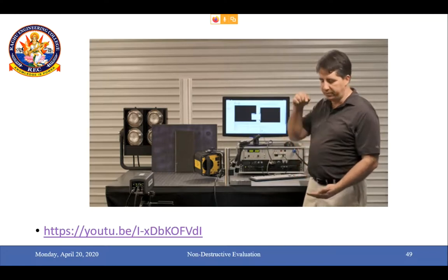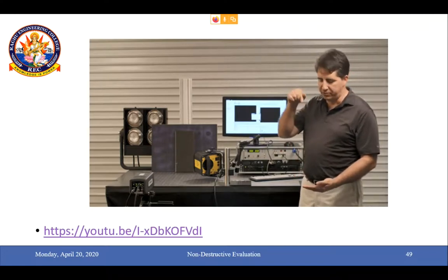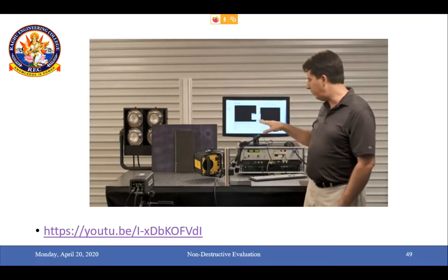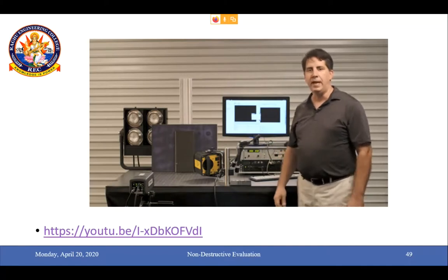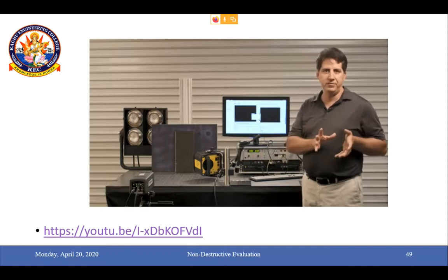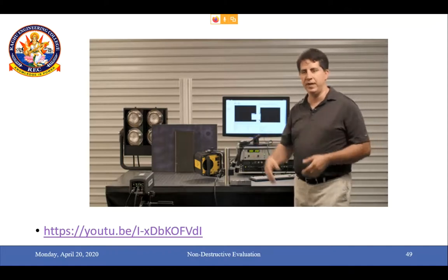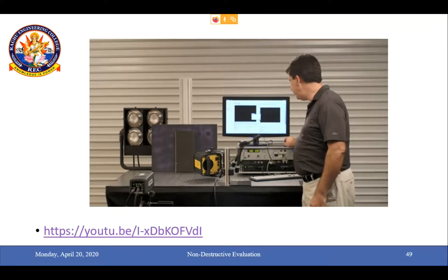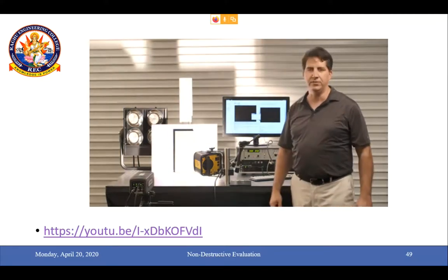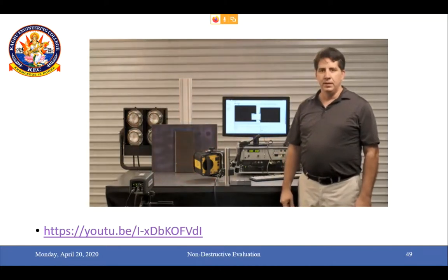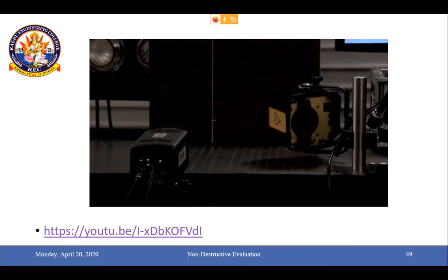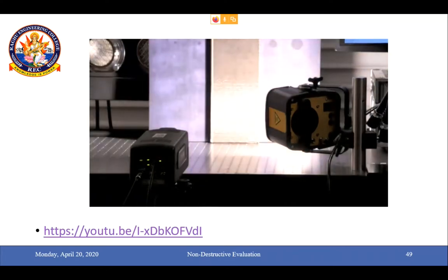And what we'll do is pixel by pixel, we'll drill down. If you drill down through that, what you should see is a graph, a sinusoidal graph representing exactly what we input with the lamp. And in those pixels where you have defects, what you'll see is that that graph is phase shifted, so it's not in line with the excitation signal, indicating that there might be a defect there. And once we have the resulting image, I'll show you what that looks like. So the entire measurement will take 20 seconds, 5 seconds on, 5 seconds off type of thing.